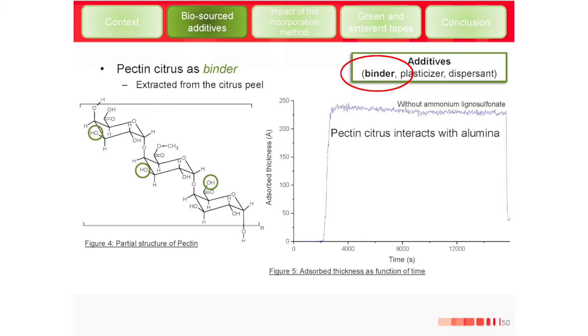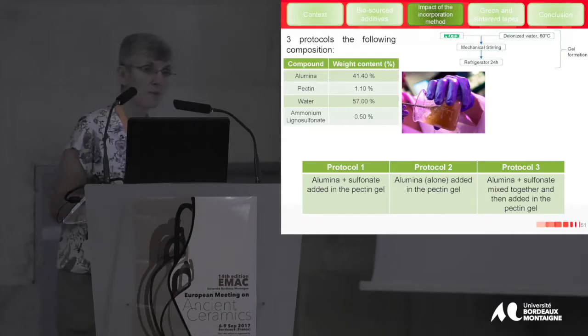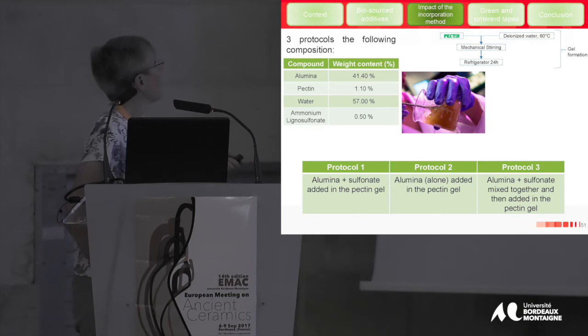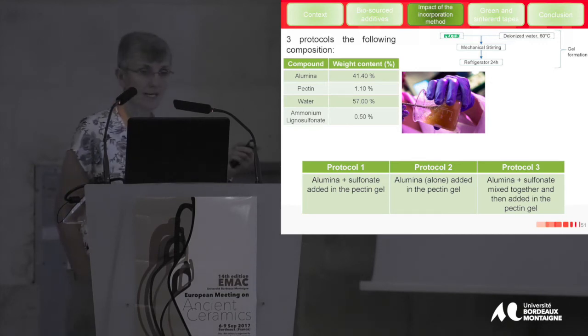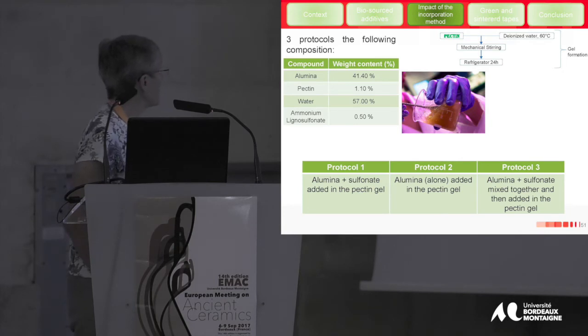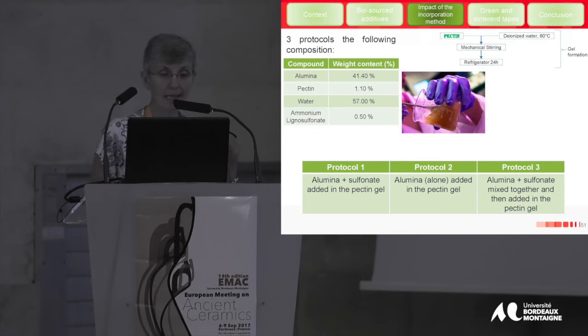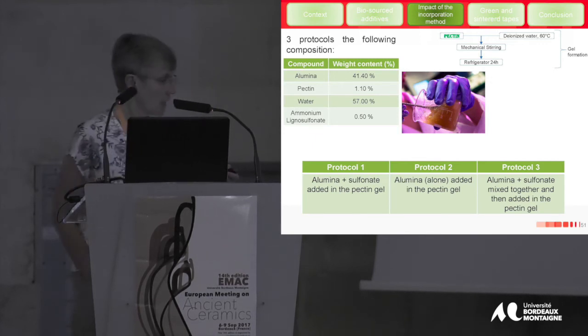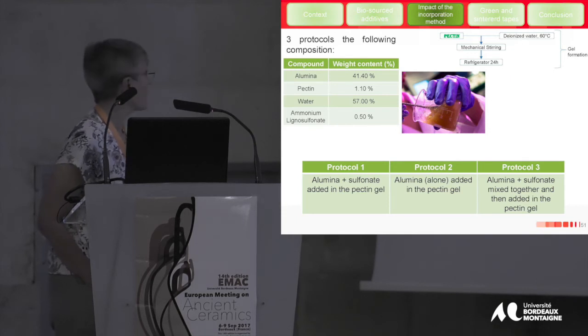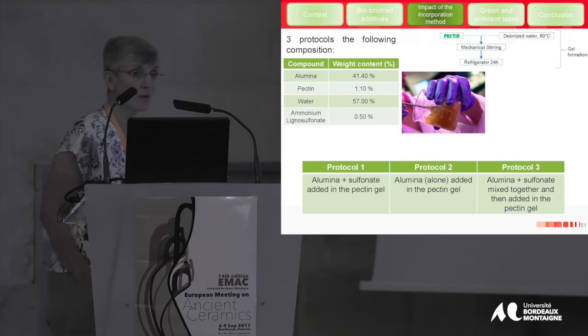Now we found a good binder, a good dispersant. We are going to prepare a suspension. First of all, we start with the pectin. So pectin, you obtain a gel, okay? And we've tried 3 different protocols to check whether there was an incidence of the order of introduction of the additive on the rheology. So we started with alumina powder, and the dispersant added in one go in the pectin gel.